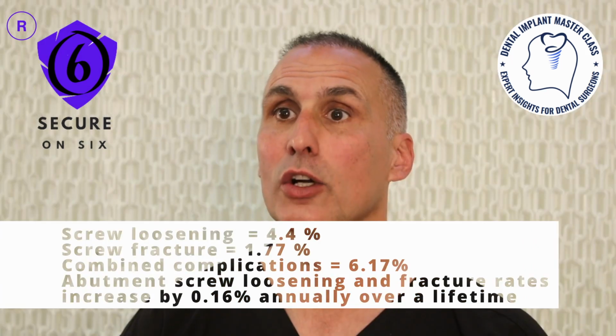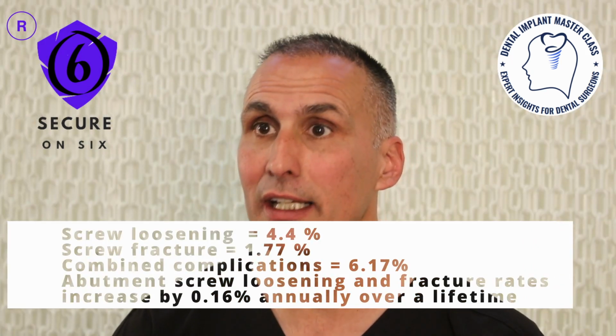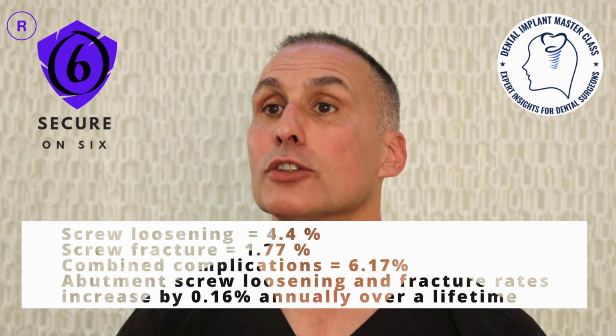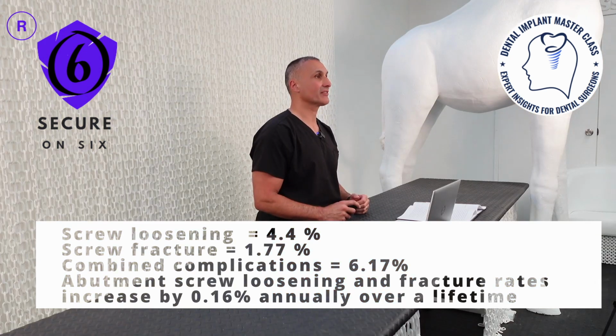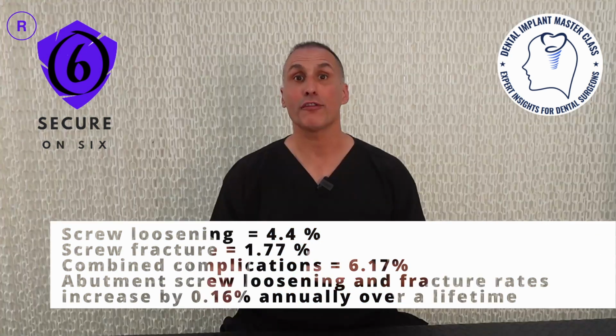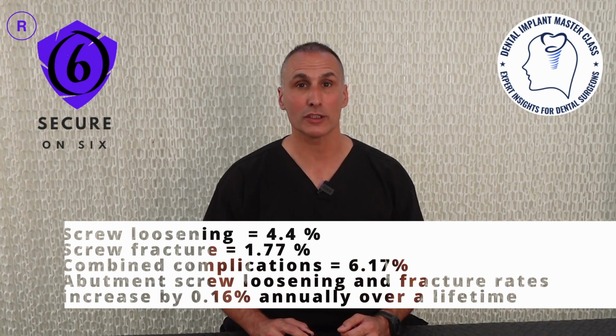In summary, over the defined period of my study, the overall mean rates were as follows: screw loosening at 4.4%, screw fracture at 1.77%, and the combined fracture and loosening rate was 6.17% of all implant screws. Unfortunately, there has been no significant improvement in this common complication of screw loosening and fracture despite technical advancements, with an annual increase of 0.16%.